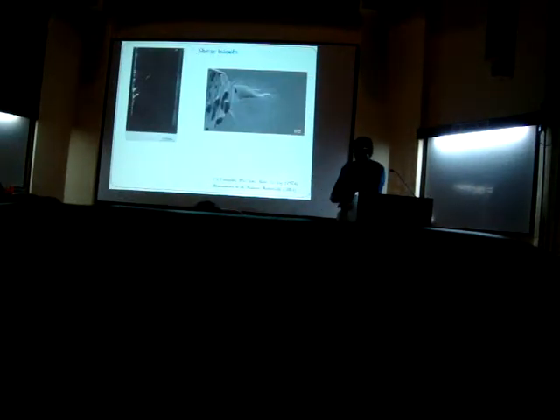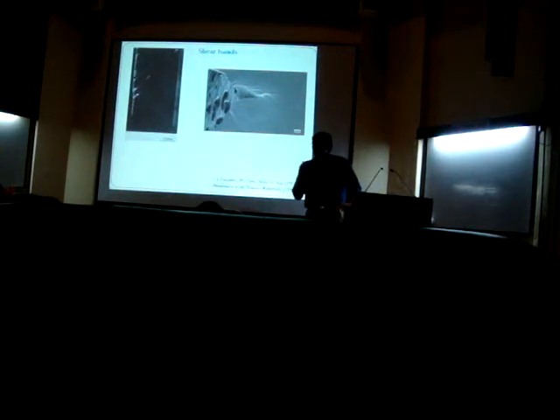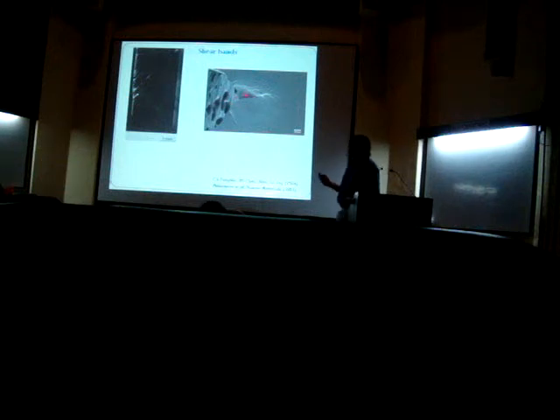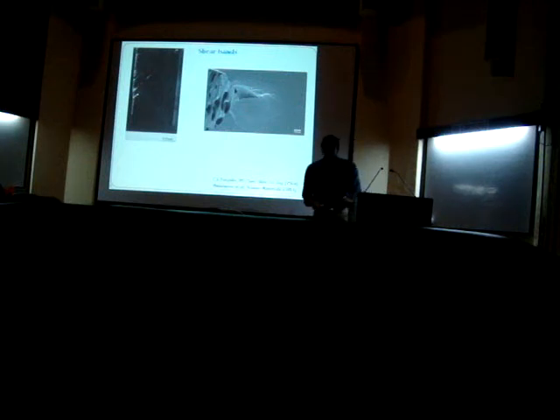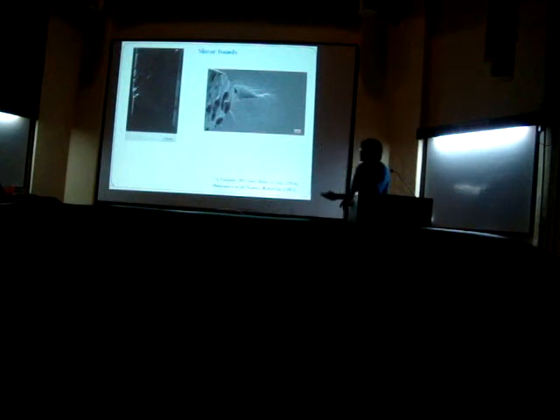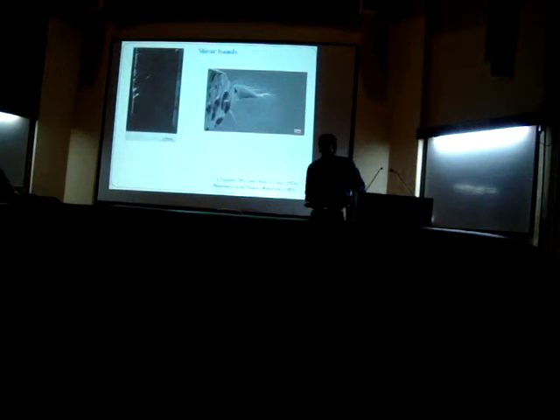So microscopically, that was the picture. Macroscopically, all these STZs collectively form something called a shear band. As you can see here, a better picture is here. This was one paper by Marius Dimitrov, whom we have collaborated with in the recent past. He shows that when there is a crack in a metallic glass and it's loaded, shear bands can form in a very dense fashion. And this actually provides a lot of crack resistance. We generally think that shear bands, as in the case of tension, can cause catastrophic failure, but it is also the only means of plasticity in metallic glasses.